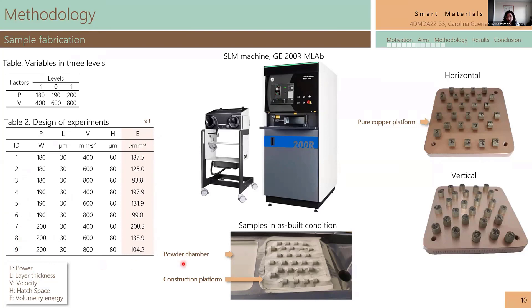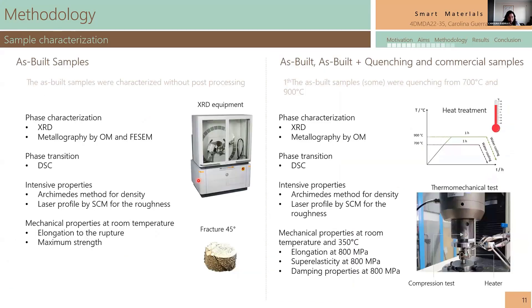In total there were nine samples. This alloy was produced in duplicate, fabricated in both horizontal and vertical orientations, with eight millimeters diameter and six millimeters height. I divided the work to distribute the characterization: first I built as-built samples to find the better laser parameters, then I chose the best parameters and compared the as-built samples with quenched samples and the commercial sample, in order to know if there is any advantage in producing this alloy by this technique.